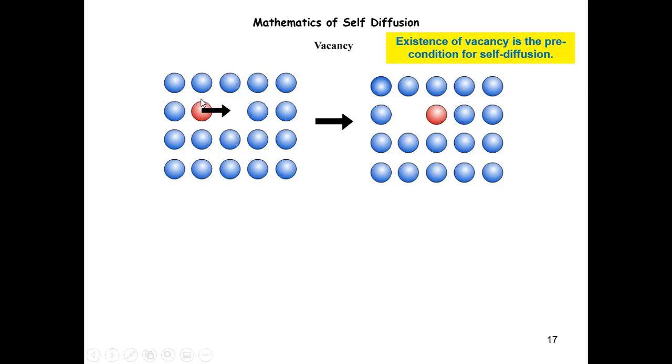If you think it's difficult to look at the substitutional particles, just think about a vacancy, right? Because the substitutional diffusion can equivalently be described by the vacancy diffusion, because these two are basically the same process, but looking at different atoms. If you're thinking there's a vacancy right here, this vacancy can hop into any of the nearby locations where there's a real atom, right? And usually we consider the vacancy concentration is low, so the majority of the neighbors are just real atoms the vacancy can hop into, right?